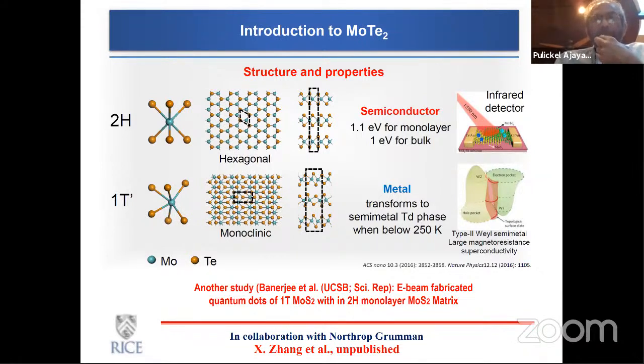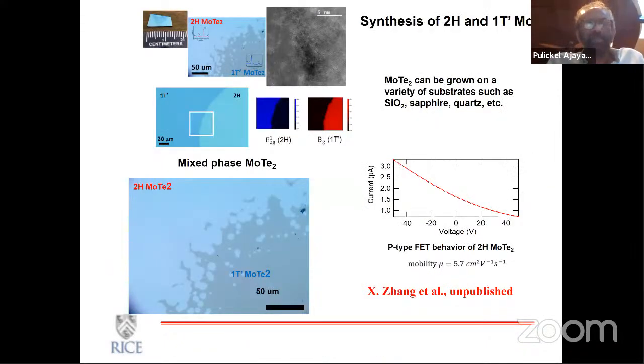But this is different because these are compositionally the same. So you could still create a two-dimensional heterostructure with the same composition of MoTe2, but different phases. So as I said before, many of these transition metal dichalcogenides have different phases. So 2H and 1T prime, one of them is semiconducting, the other one is metallic. And if you try to grow MoTe2 just under a range of conditions, typically you end up with a mixture of these two phases. Thermodynamically, they're kind of similar in energy. And if you see that image, you can see there's a 2H and the 1T prime, which is slightly different in structure, although the lattice parameters are rather close. So you could get these rather strained but in-plane stitched together heterostructure.